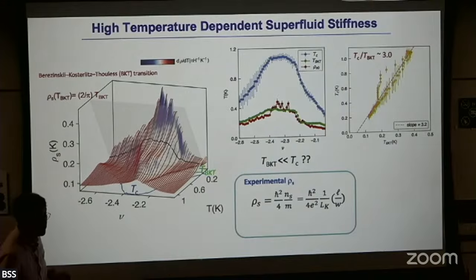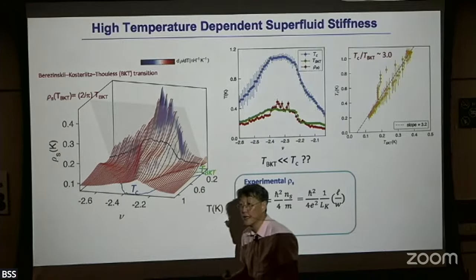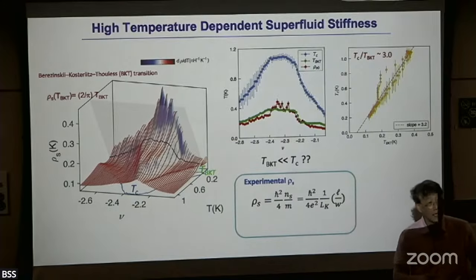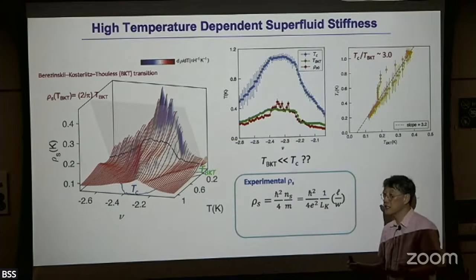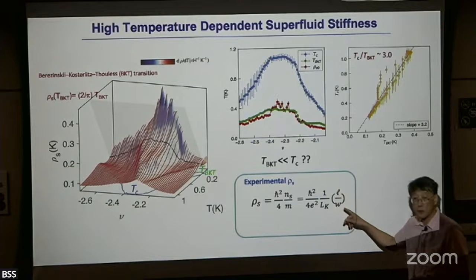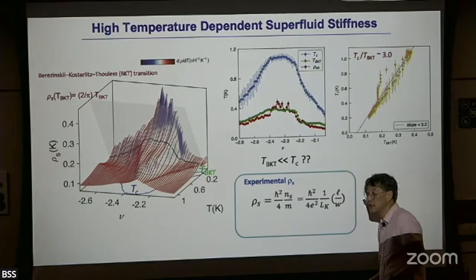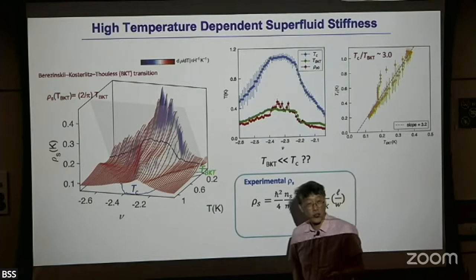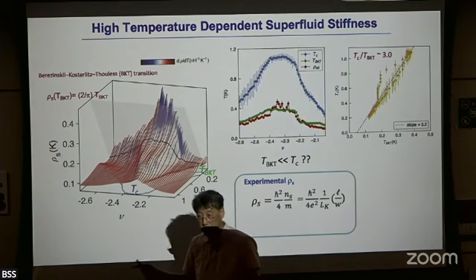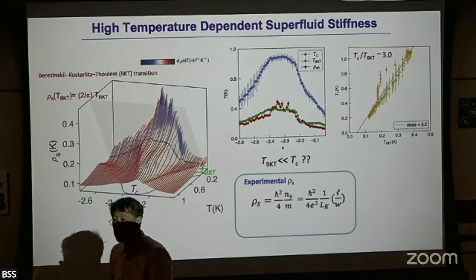To convert into the superfluid stiffness, an intensive quantity, I have to normalize with my sample size, length and width, like resistance converted into resistivity. Although the trilayer is better than twisted layers, there are still enough disorders in the sample, and you have to deal with this disorder.